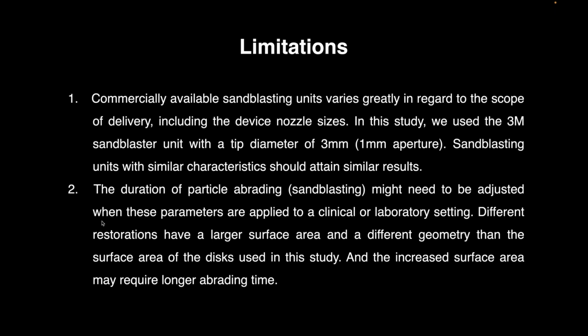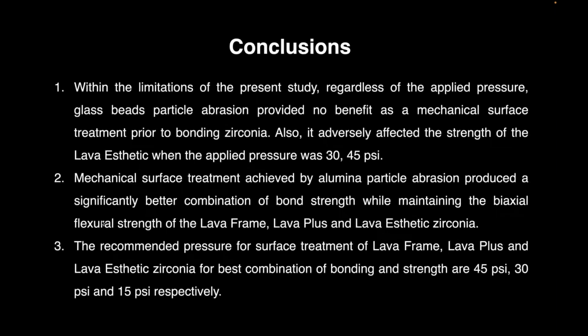So the conclusion of this study: within the limitation of the present study, regardless of the applied pressure, glass beads particle abrasion provided no benefits as a mechanical surface treatment prior to bonding zirconia. Also, it adversely affected the strength of the Lava Esthetic when the applied pressure was 30 or 45 psi. Mechanical surface treatment achieved by alumina particle abrasion produced a significantly better combination of bond strengths while maintaining the biaxial flexural strength of the Lava Frame, Lava Plus, and Lava Esthetic zirconia.